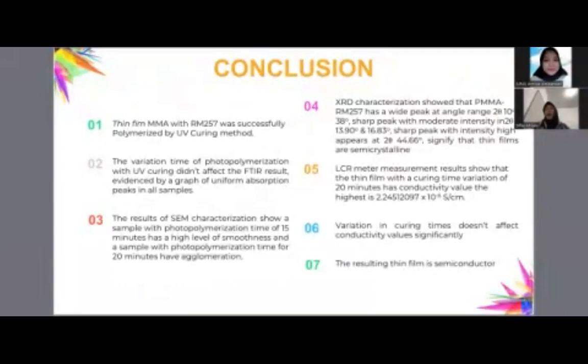First, thin film PMMA with RM257 was successfully polymerized by the UV curing method. Second, the variation of photopolymerization time with UV curing didn't affect the FTIR result. Third, the SEM characterization result shows a sample with photopolymerization time of 15 minutes had a high level of smoothness, and a sample with photopolymerization time of 20 minutes had agglomeration.